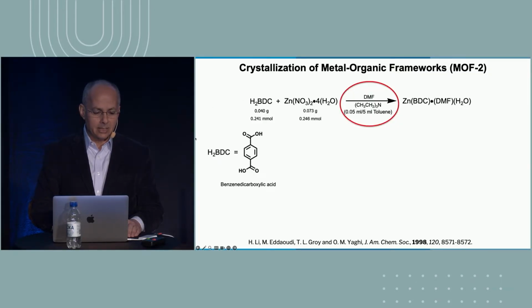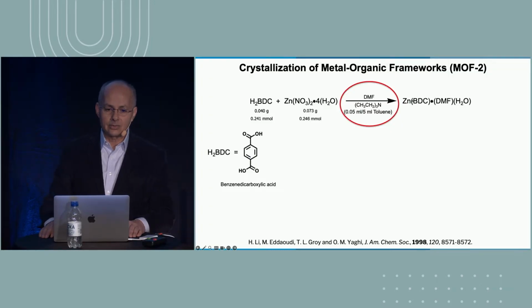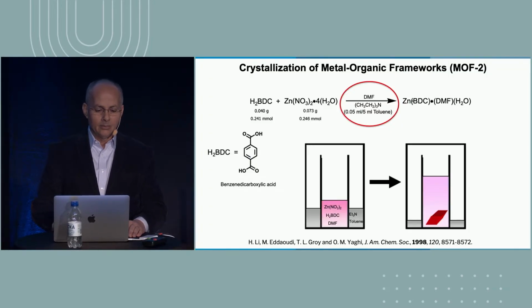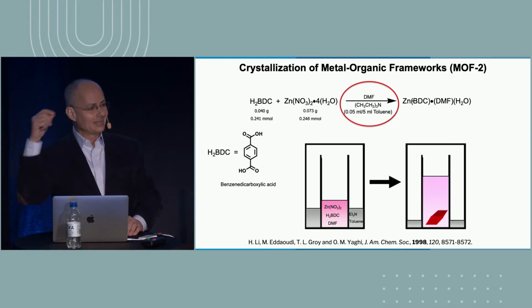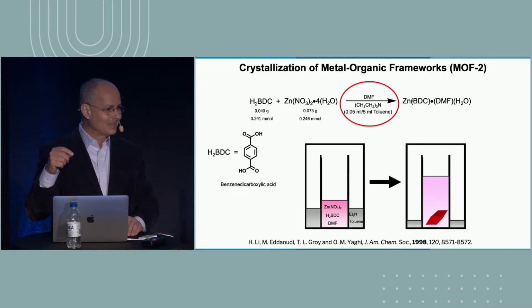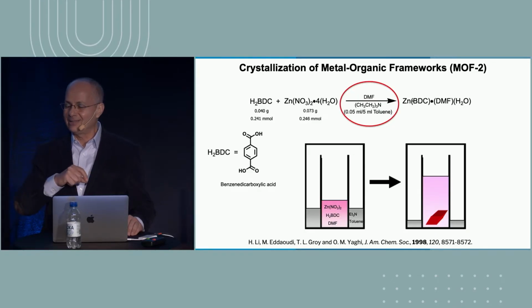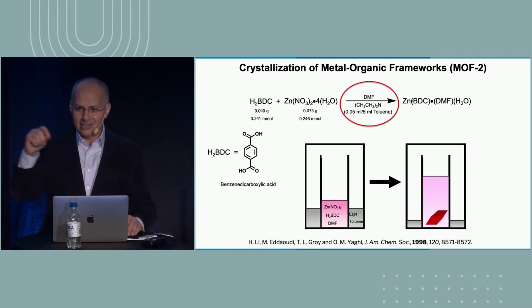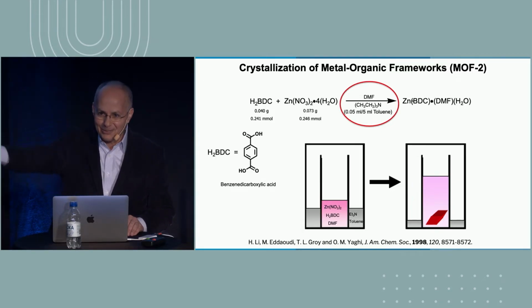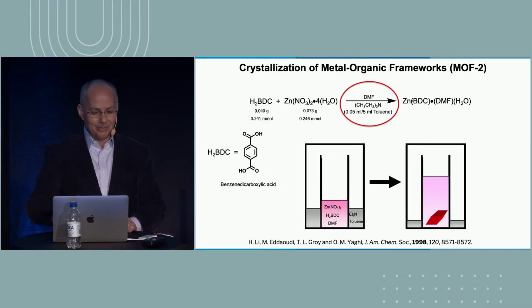What we did is to take the acid, this diacid, dicarboxylate, a very common material called terephthalic acid, and a solution of zinc nitrate, very simple reaction. Under these conditions, you can crystallize an extended structure. Well, how does it work? What made it work is, of course, a student that I met when I was on an internship in China. And when I became assistant professor, he wrote me a handwritten letter that said, "Professor Omar, I see that you're a professor at ASU, and I see that you're making these extended structures."